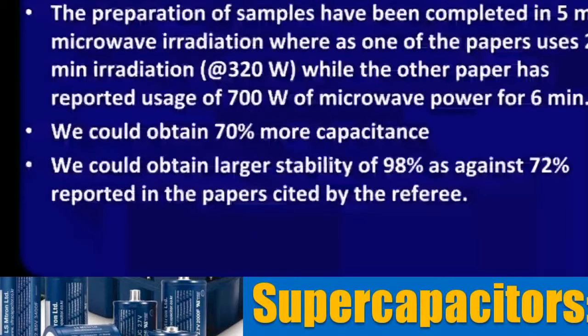That means in 5 minutes we use only 320 watt of the power and we got excellent material, and the improvement in capacity was phenomenal. There is a 70% increase in the capacitance. For want of time, I have not shown another important aspect, which is known as the cyclic stability.